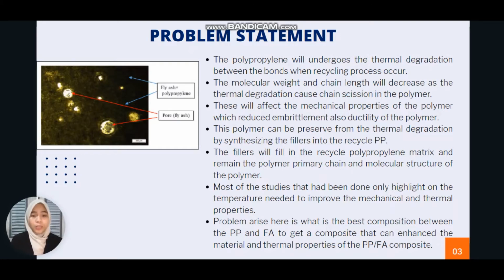So this polymer can be preserved from thermal degradation by synthesizing it with a filler to improve the recyclability, which in this project is fly ash. So the filler will fill in the polypropylene matrix and maintain the polymer chain and molecular structure of the polymer.